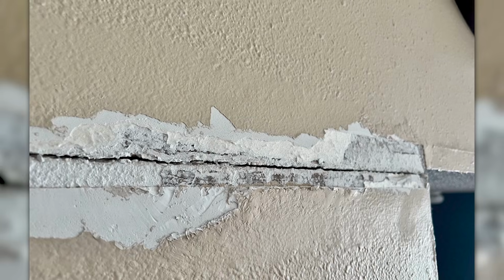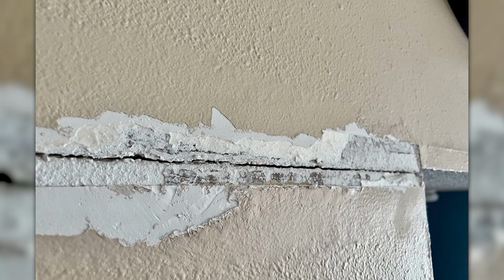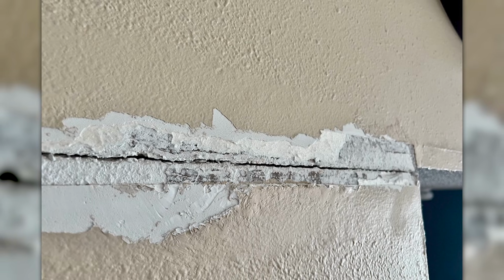There is always a small amount of uncarbonated lime in the mortar, free lime. When a crack forms, water enters. That water dissolves the free lime. The dissolved lime migrates into the crack, and when it dries, it recrystallizes. The crack seals, not completely, not instantly, but over time, small cracks in lime mortar can close up. The wall heals. Drywall does not do this. Portland cement does not do this. Once they crack, they stay cracked.